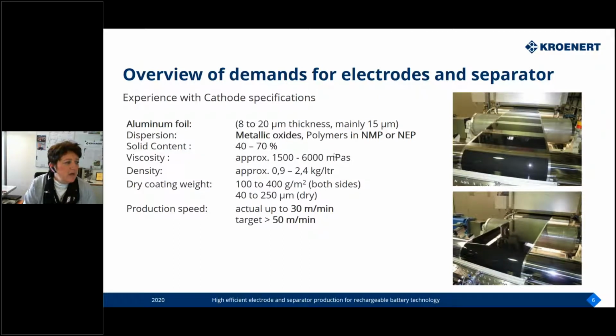So from the cathode side, usually aluminum foils are used. We handled already very thin films up to 8 micrometer, so very sensitive materials. The usual solid content of such chemical solutions is between 40 to 70%. Viscosity 1,500 to 6,000. More important is that usually these materials are thixotropic, which means they are changing the viscosity, or shear thinning, related to shear force, and this you need to evaluate when you handle such systems. Dry coat weight usually between 100 and 400 GSM, depending on the kind of the battery.